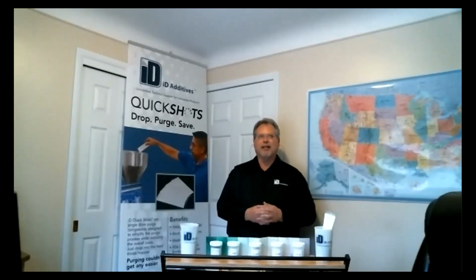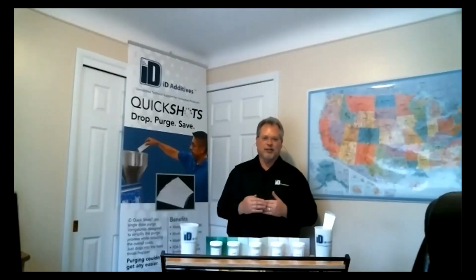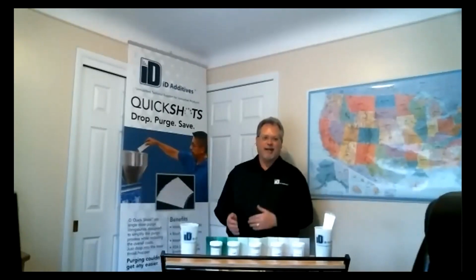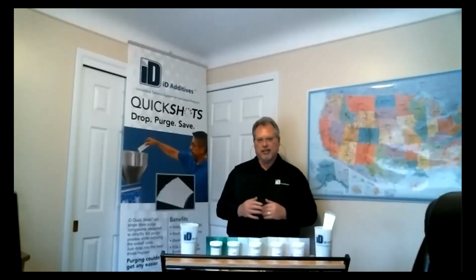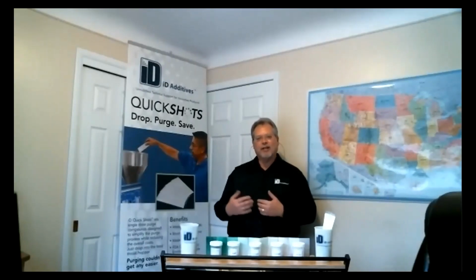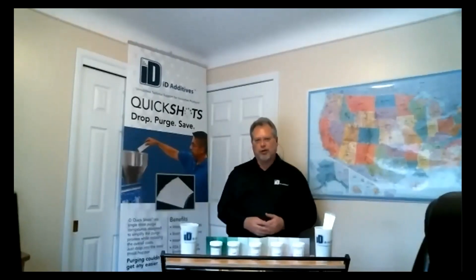And I believe this was on a Santoprene part, and so that showed them that with a good purge compound and a good maintenance program, they need to do it after every change, so they don't get that layered up effect. That took a little bit longer, but once they introduced their purge program, they said the changeovers were only taking 10 to 15 minutes, and they didn't have any more issues after that.